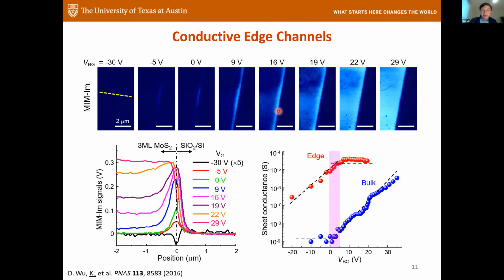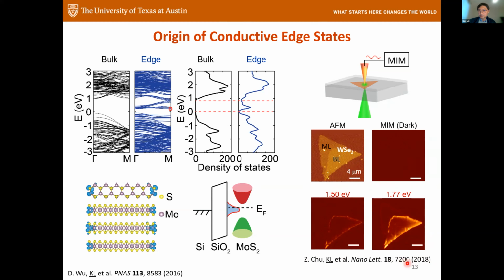As you shine it with a below-gap laser, you see the monolayer and bilayer are still insulating, but the edge starts to show up, the bilayer edge. Then you increase this, and the monolayer edge also starts to become bright. In this paper, we went all the way to very high photon energy, and then everything. Please. Any particular reason the bilayer edge shows up first, and then the monolayer edge?